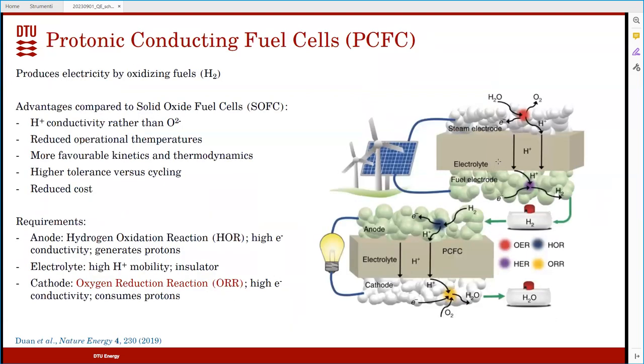But then, as I said, chemistry agnostic, technology agnostic: fuel cells. If you do water splitting, then you form hydrogen and oxygen. But how do you recombine them to make electricity? One way is fuel cells. Here we started looking at proton conducting ones, because you conduct protons instead of oxygen vacancies, so it's faster. You have a lower operational temperature. The kinetics and thermodynamics are better. You have a higher tolerance for cycling and much lower cost. You can use simple ceramics. But then you require an anode that is able to do the hydrogen oxidation reaction.